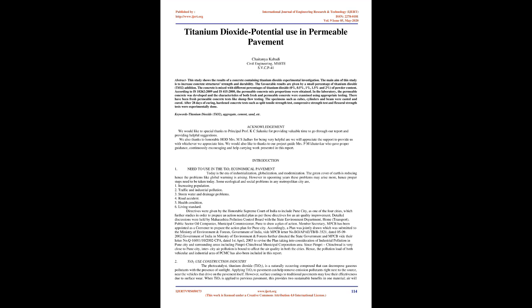The concrete is mixed with different percentages of titanium dioxide: 0%, 0.5%, 1%, 1.5%, and 2% of powder content. According to IS 10262:2009 and IS 456:2000, the permeable concrete mix proportions were obtained.